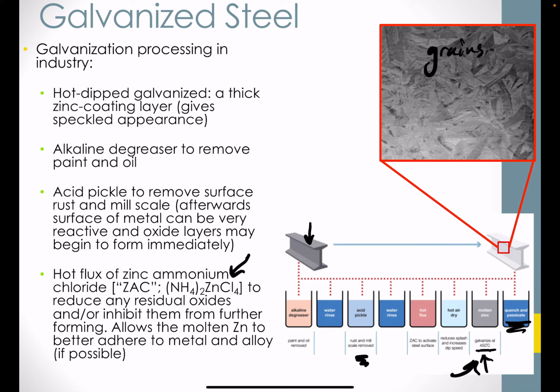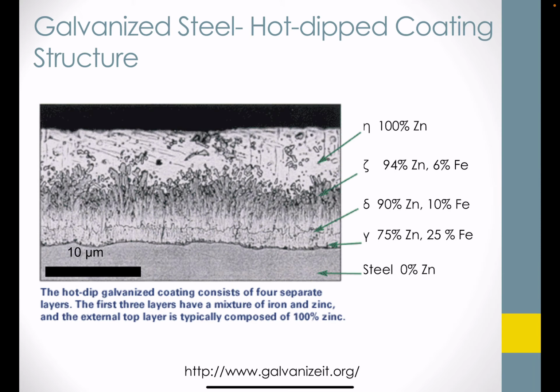Okay, and then we mentioned that we dip the final sort of prime structure after the ZAC step into molten zinc for a final thick application of a zinc coating from a liquid state at about 450 degrees C. Quenching, of course, is necessary to bring the structure back to room temperature and to rinse off any excess, and that's typically done here with water. The cross-section of the hot dipped structure has been investigated. And so here's a nice electron micrograph where we've used scanning electron microscopy to interrogate the cross-section.